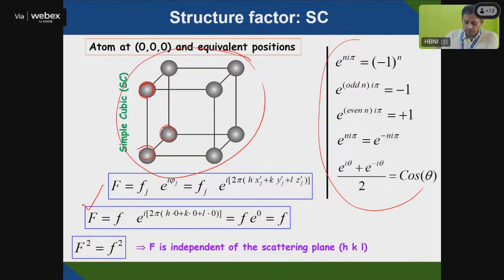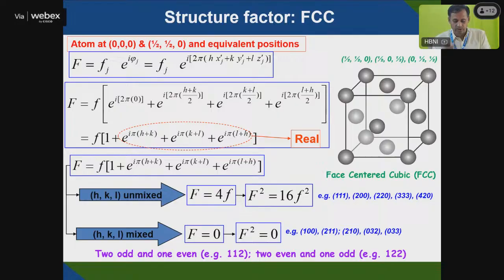So the structure factor F depends only on the atomic one in this case. So F equals f, and F square equals f square, independent of the scattering from the HKL plane, because the atom is at the 0, 0, 0 position. But if you take the FCC structure, F square will be equal to 16 f square when HKL are unmixed. If HKL are mixed, such as 0, 1, 0, 0, 2, 1, 1, the structure factor is 0. Only planes like 1, 1, 1, 2, 0, 0 with HKL unmixed will give you a nonzero structure factor, in case of FCC.